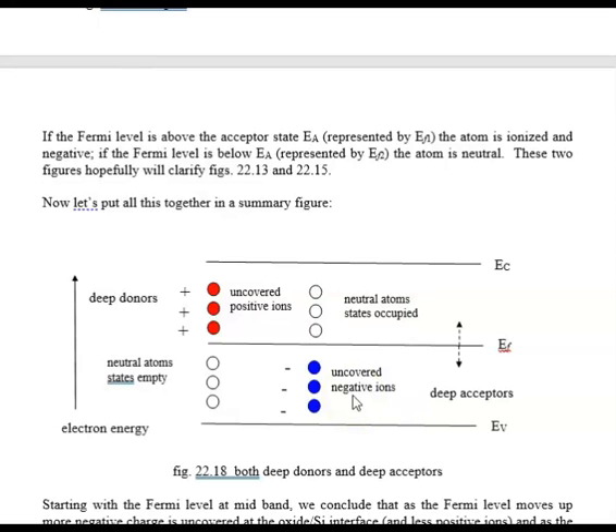And that is covered completely in one big picture right here. So let's see if we can understand this a little bit better, because this has basically everything included, and it's the key to figuring out why this is not a good thing to have interface trap states. This is the donor part. This is the acceptor part. So if the Fermi level moves up, then I have more of the red circles. If the Fermi level moves down, I have more of the blue circles. And that basically tells the whole story.